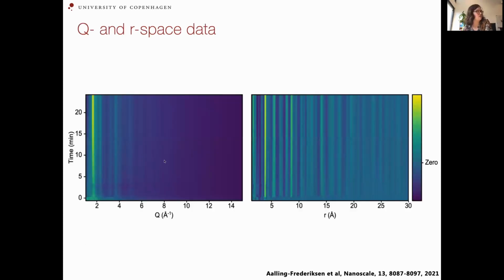So the data that we get out from this is something like this. Here we have Q, which you could also just think of as a scattering angle, and then time, and then intensity is shown in this contour plot. What we see here is that in the beginning, down here at 0 minutes, we have only broad diffuse scattering where there are no Bragg peaks. And then after a little while, we get some broad Bragg peaks.